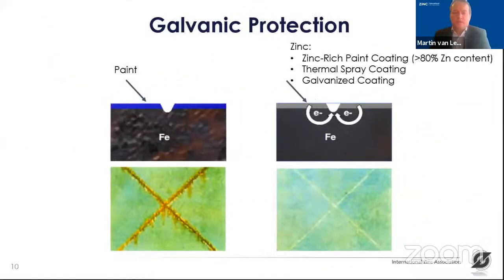It is also depicted in this overview. At the left side, you see a schematic picture of a steel substrate, which is protected with non-zinc containing paint coatings. Once the paint is compromised and you have a corrosive environment, you can immediately see the formation of red rust in the damaged areas. But if you apply a coating which contains zinc, which can be a zinc-rich paint or thermal sprayed coating or a galvanized coating, the zinc will act as an anode and will protect the steel against this red rust formation.